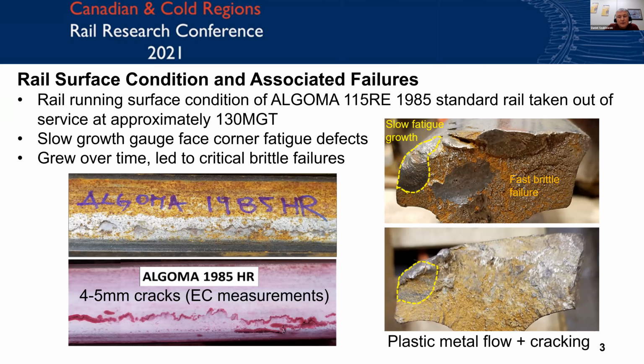Looking at the fractography of the surfaces that led to the failures, we saw that there was a slow growth fatigue component, and this is the area circled with the dotted line. It's slightly bigger than a big size button, and that grew slowly over time. So what happens is, once you get this type of crack and it progresses to a certain size or a certain percentage of the cross section of the entire rail head, the rail head cannot bear the excessive load that's being placed on it. That, added to the notch sensitivity right at the root tip of that crack, leads to the brittle failure. So you have a slow growth component, and that's in yellow, and then a fast brittle component that's cracking much quicker. It's almost instantaneous.